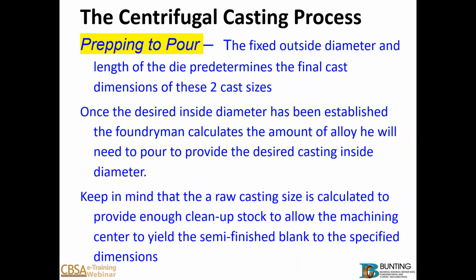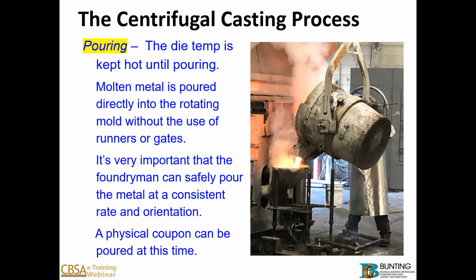Okay, prepping to pour. 2 sizes are controlled by the die. That's the outside diameter and the length. We calculate the pounds of metal required to give us the required ID. The weight calculation of the alloy also includes the amount of metal that needs to be machined off. The die temp is important, as well as the pouring spout and then the ladle temperature. Everything has to be kept at the perfect temperature so that the metal pours into the die evenly. When we're pouring into the mold to produce the casting, at the end we can also produce a coupon, and this coupon is used for people who require chemical or physical testing afterwards.